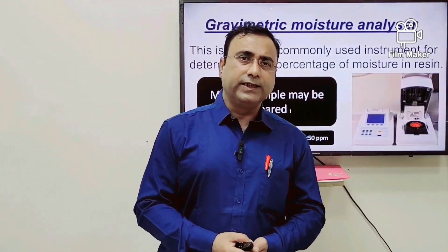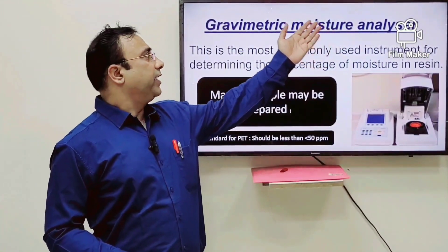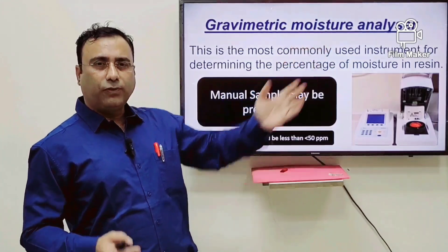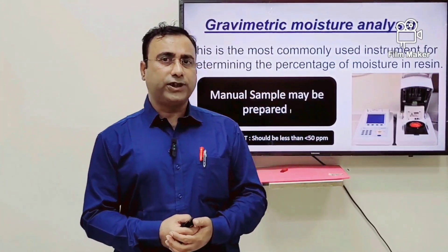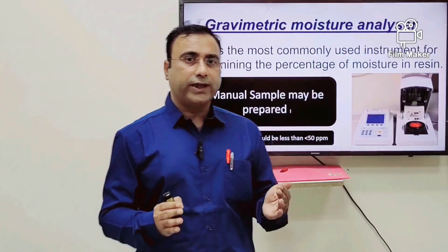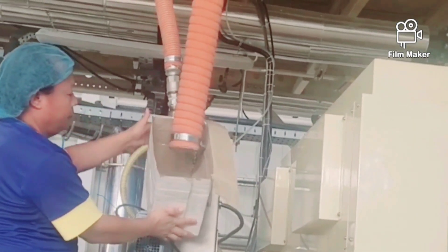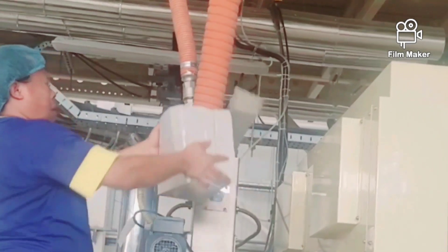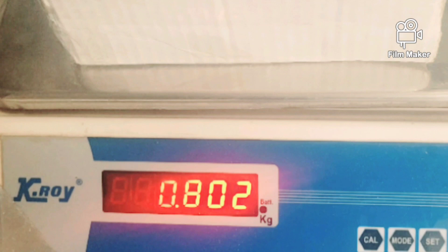To analyze moisture, larger companies use a moisture analyzer in their quality lab. For smaller companies that cannot afford this equipment, I suggest a method I have implemented: when your machine is running well and all cavities produce good preforms, weigh a sample of material in a box and record that weight. When you face this problem again, repeat the exercise — if the material weight is higher, that indicates moisture content.